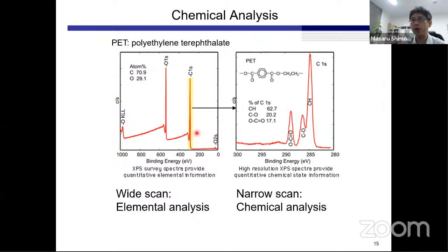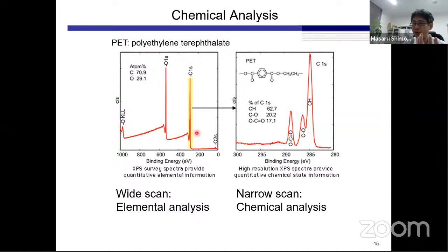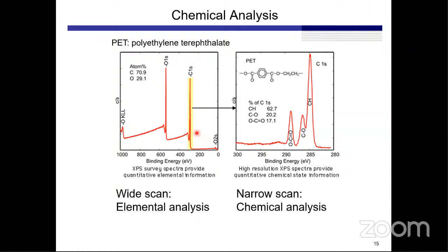Otherwise, there is a possibility of two different Fermi level materials, like non-conductive ones. If you have non-conductive materials and they are not touching each other, then the peak becomes broad. And if one sample is very highly charged and the other one is not so highly charged, then there become two peaks. So depending on the electronic conductivity, you have to doubt the different charging up effect. So these are the reasons for the satellite peaks.